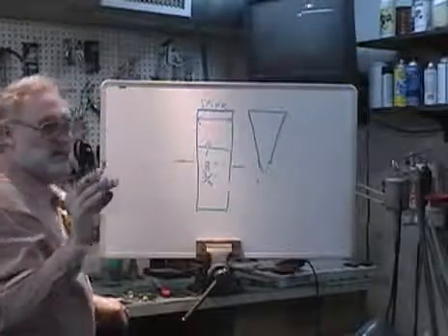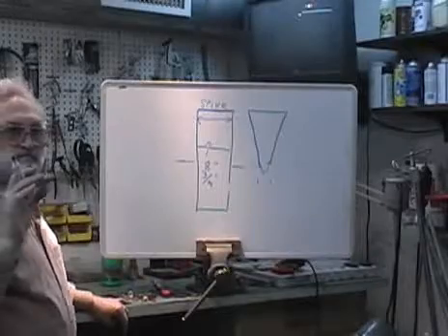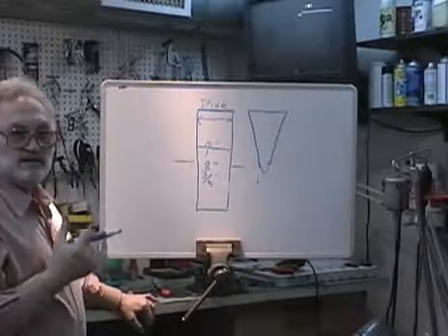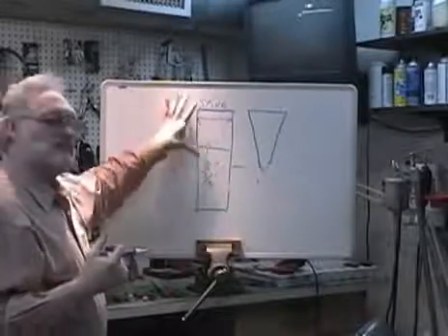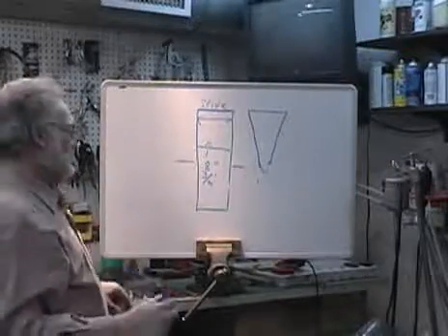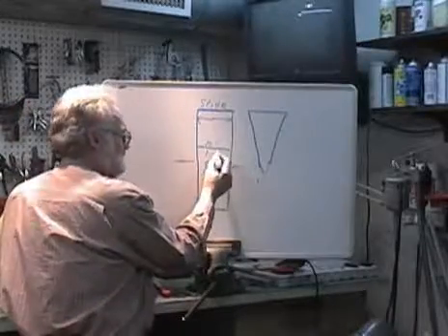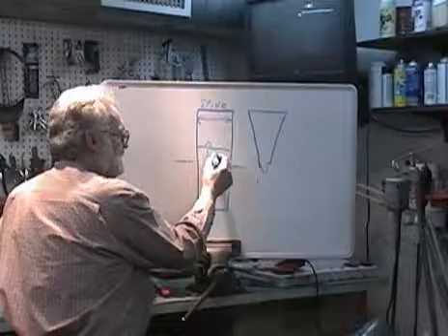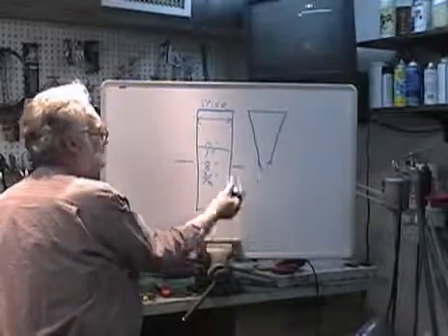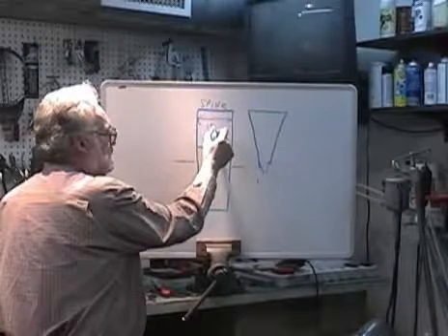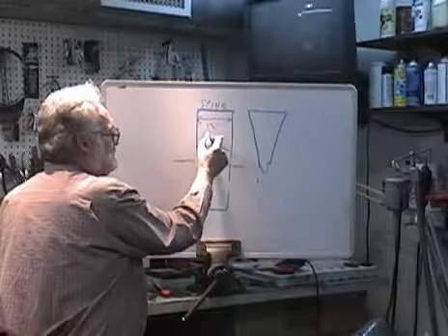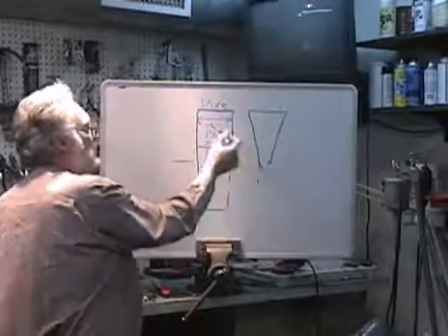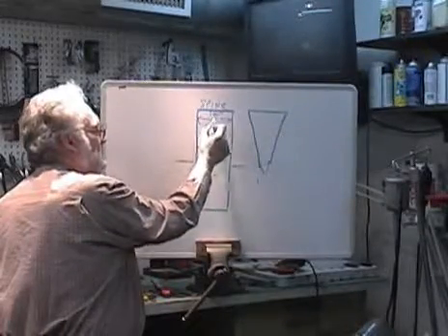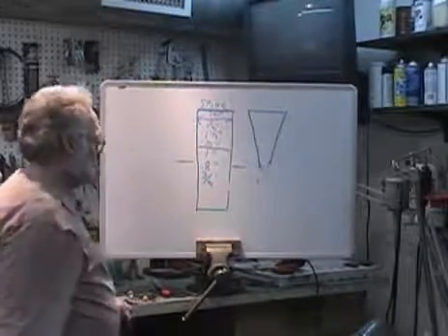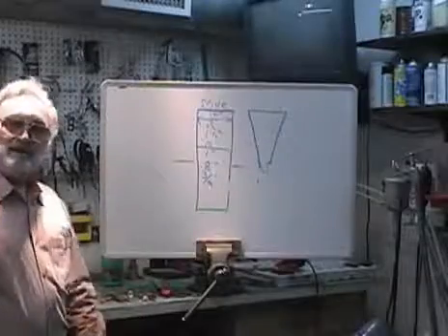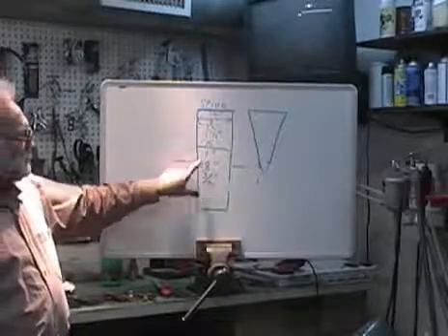And these are not right on the money, because with experience, you can actually grind this whole 2-inch blade here with an 8-inch wheel. I've done it before, but you have to be a very experienced grinder to do that. So with a 10-inch wheel, you can grind approximately 1 inch up the blade. With a 12-inch wheel, you can grind approximately 1 1/2 inches. And with a 14-inch wheel, you can grind about 2 inches. Don't take that to the bank, because somebody will prove me wrong. But these are approximates here.